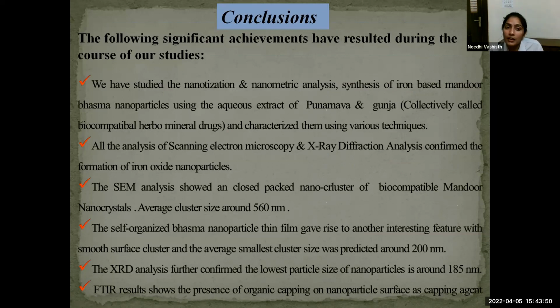So the conclusion is we have studied the nanotization and synthesis of iron-based Mandur Bhasma nanoparticles using the aqueous extract of Punarnava and Gunja, collectively called a biocompatible herbo-mineral drug, and characterized them using various techniques. The analysis by scanning electron microscopy and X-ray diffraction confirmed the formation of iron oxide nanoparticles. The SEM analysis shows closely packed nanocrystals of biocompatible Mandur nanocrystals, with average cluster size around